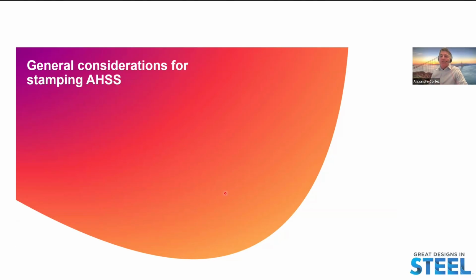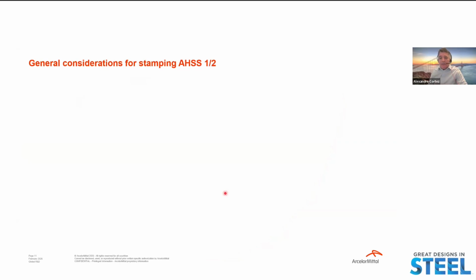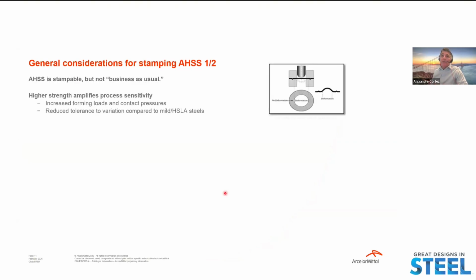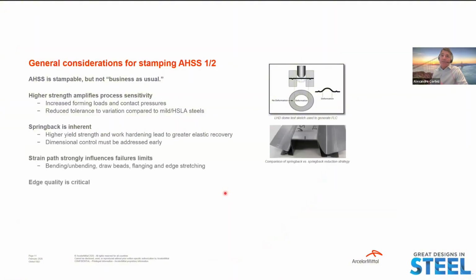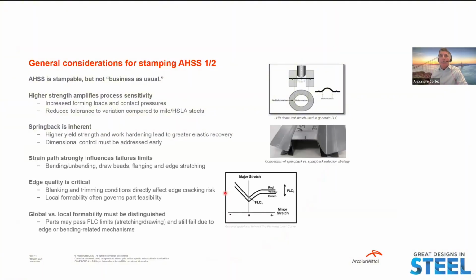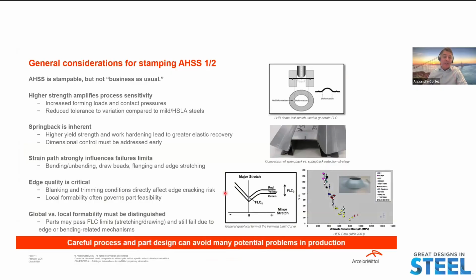With that foundation, let's shift to stamping, starting with general advanced high-strength steel realities. I would like to highlight some considerations for stamping. Advanced high-strength steel is stampable, but not business as usual. Higher strength amplifies process sensitivity. Springback is inherent to this kind of grade. Strain path strongly influences the failure limits. Edge quality is critical. Blanking and trimming conditions directly affect the edge cracking risk. Local formability often governs part feasibility, and global versus local formability must be distinguished.